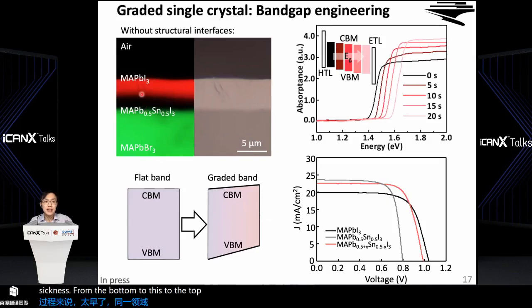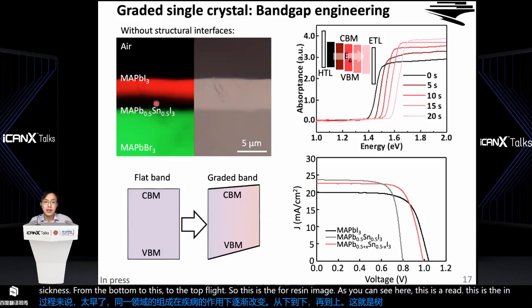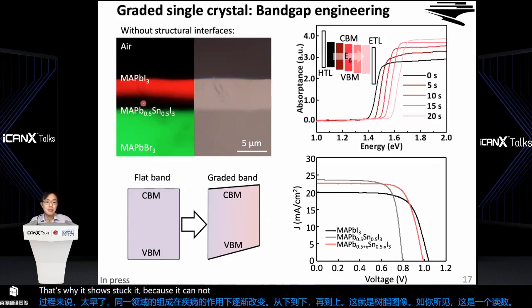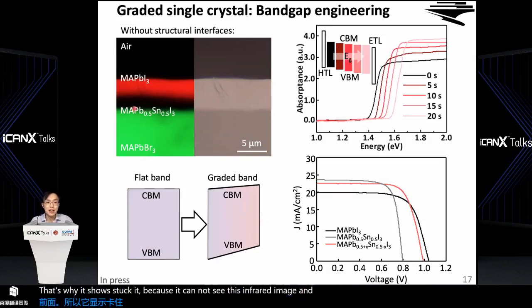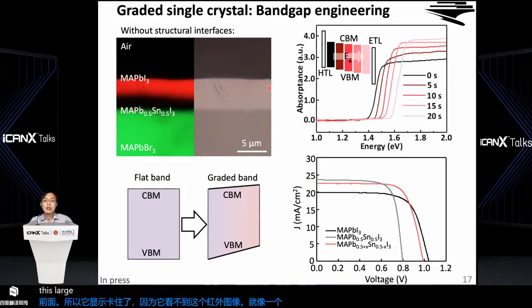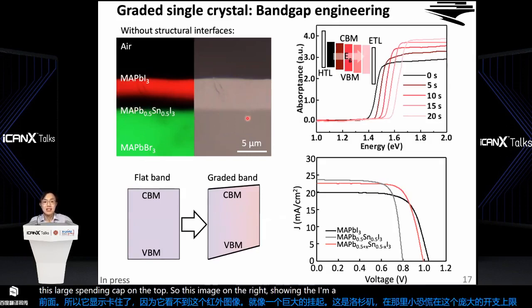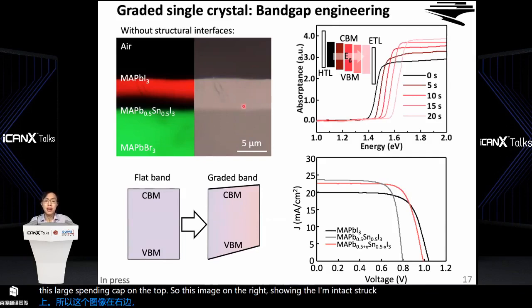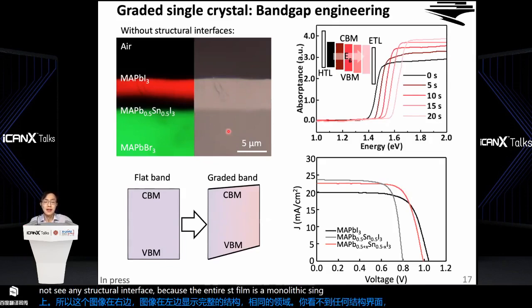So this is the fluorescent image. As you can see here, this is red, this is the infrared. That's why it shows dark here, because you cannot see this infrared image. And this is like a very small band gap, this large band gap on the top. So this image on the right showing the intact structure of this thin film. You do not see any structural interface because the entire thin film is a monolithic single crystal without any interface that would otherwise reduce the carrier transport mobility.